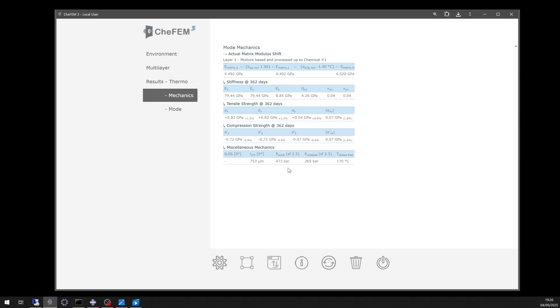A separate run, corresponding to an exposure time of only a few minutes, so without noticeable water uptake in the composite, gave 274 bar. Thus, the difference between the dry and fully saturated conditions is only 16 bar at the node evaluated.